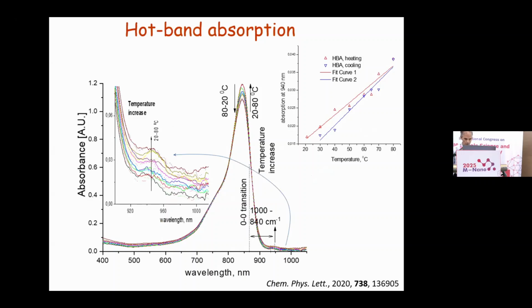Also, I will tell about hot band absorption. That means that when we excite an electron not from the ground state, but from some vibrational energy level, this process is called hot band absorption. This process is also dependent on the temperature. The higher the temperature, the more intensive hot band absorption we can observe. In principle, this hot band absorption can be observed like a small band from the lower energy tail regarding the fundamental absorption of the material. Again, the integral intensity of this absorption increases with temperature and decreases when the temperature is decreased.